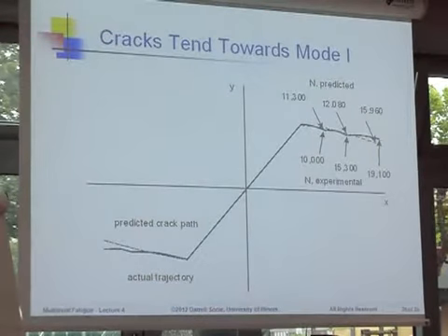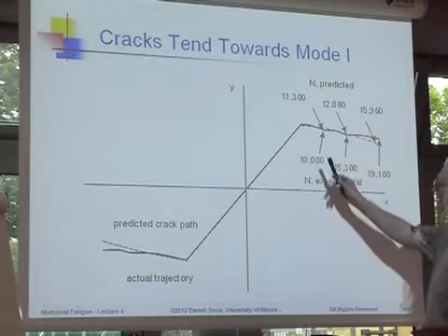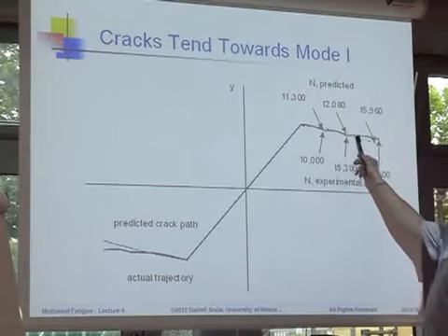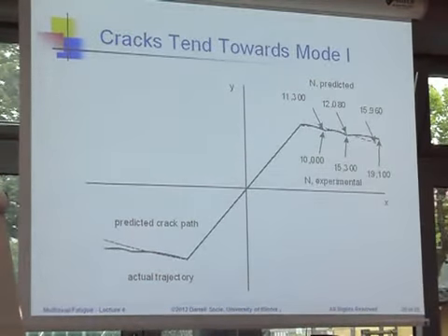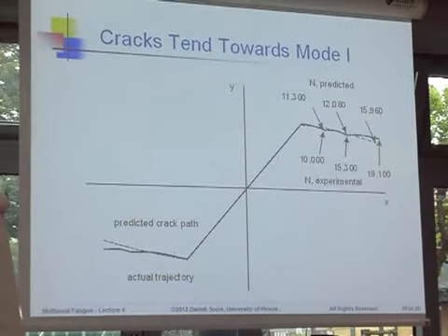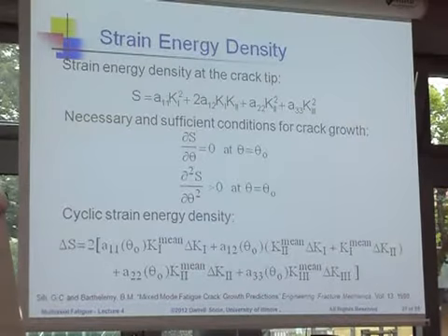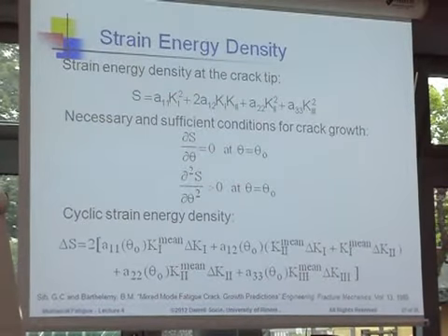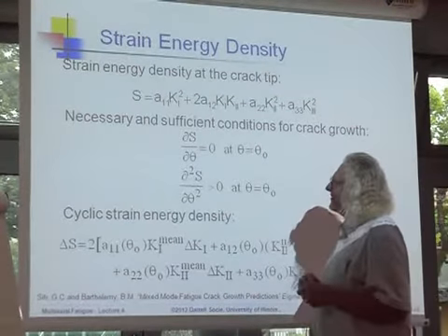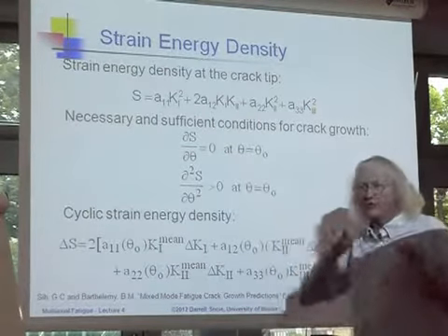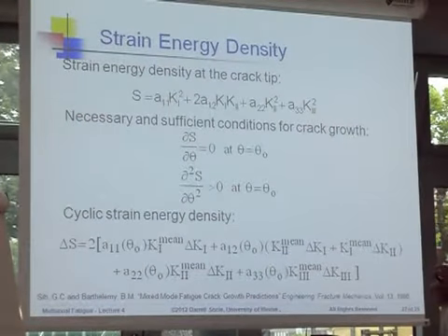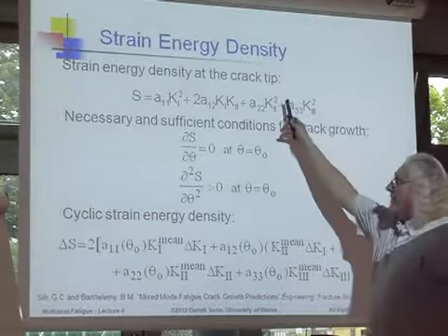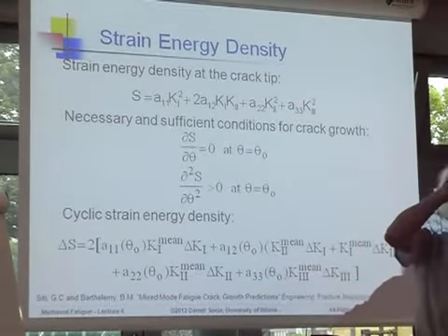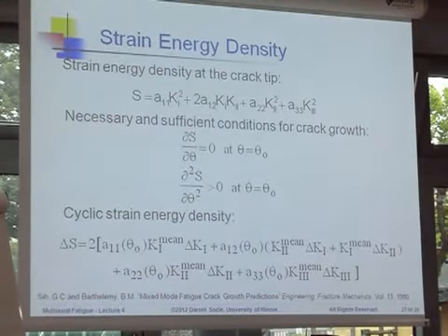And then, of course, there's some modeling. That's done. You may need this tomorrow. You start out with an angled crack like this, and you try to predict what the crack path is as it grows. There are a couple of ways that people try to do this, and the most useful one is the strain energy density criterion. This is by Sih. You essentially calculate a strain energy density, and there are the formulas for doing it. It's combinations of the stress intensity in mode 1 and mode 2. If you want a crack to grow, you simply look at where the maximum strain energy density is, and the strain energy density will change as the crack grows, and you make predictions like on the last slide.